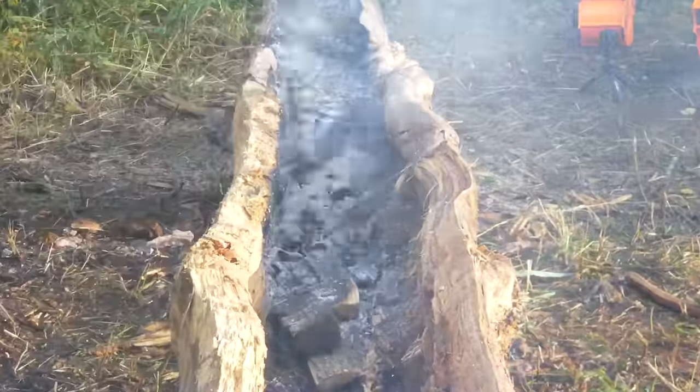You're gonna just sprinkle it on, then add alternating layers of more charcoal to act as a reducing agent, and then just blow into it for about an hour or so. I'm gonna try putting the cover on top to help seal in and trap the heat, keep it contained. Likely add charcoal as we go. And hopefully when it's all done, we can collect some little pearls of copper at the bottom. Collect enough of them and you can cast them.